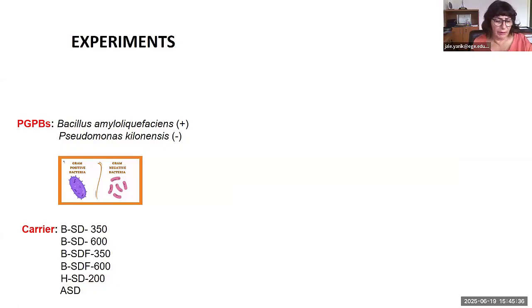Although most previous studies have reported that biochar can enhance soil microorganism communities, the effects of biochar on different microorganisms can be quite different. The composition and physicochemical properties of biochar derived from different biomasses differ, thus their effects on organisms should be different. For instance, researchers observed an improvement of microbial growth when using poultry litter-derived biochar, whereas they observed an inhibition of the same microorganism community when using pine biochar.